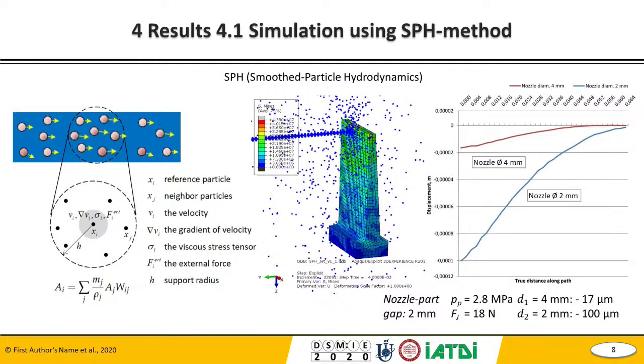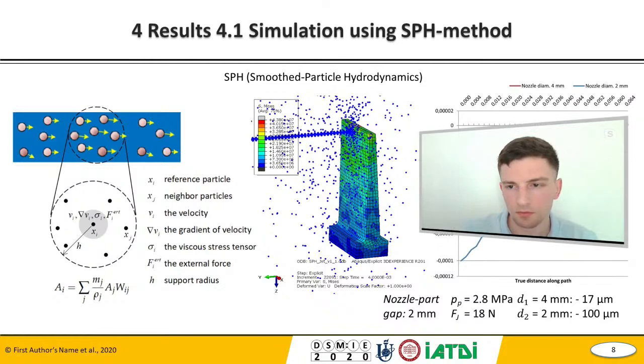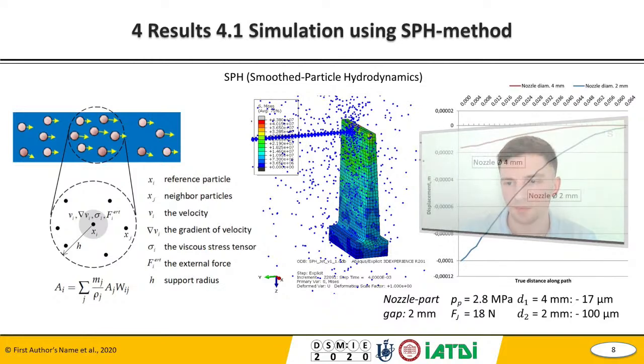For different nozzles, we noticed that the deflection with the nozzle of 2 millimeters diameter is near 6 times greater than with 4 millimeters in diameter. The input parameter was pump pressure, and the gap between the nozzle and the wall was 2 millimeters. Next slide, please.